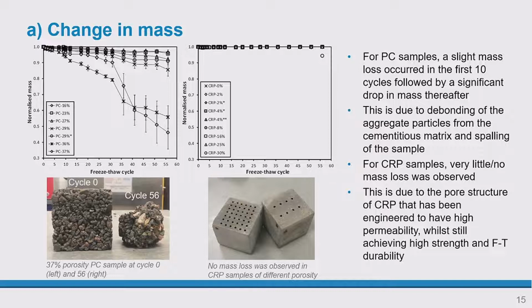So on the y-axis, we have the mass of the samples of different porosity, and on the x-axis, we have the freeze-thaw cycles. Depending on the porosity of the permeable pavements, the lower the porosity, the less loss in terms of mass. The higher the porosity, as you would expect, the more mass it loses. So in the worst case scenario, when it had about 30% porosity, it lost more than 50% of its mass, which is quite detrimental, because in real life that meant you need to completely resurface that pavement. Whereas in the case of CRP, it kept its mass.